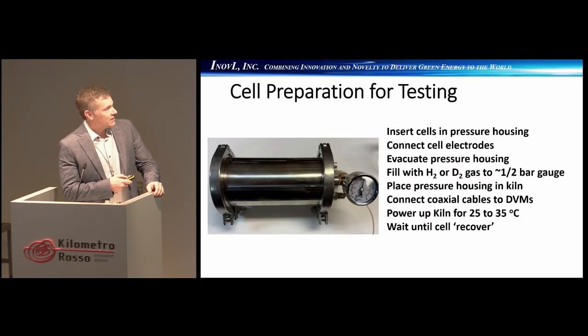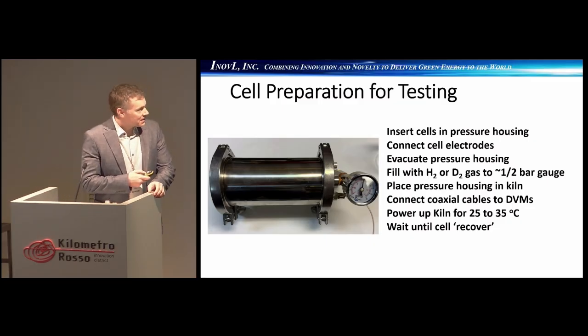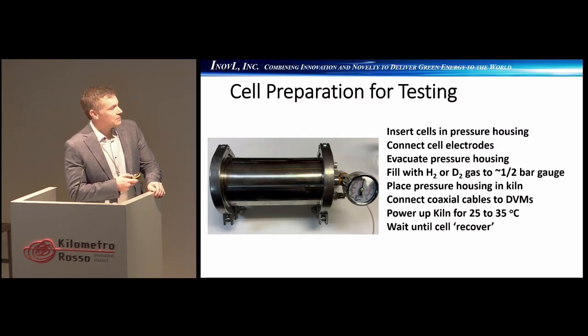And here's just kind of an example of one of our pressure vessels that we use for testing. And just kind of a little bit of housekeeping here of our testing procedure at the time when we were running some of these tests that we're reporting on. Our pressure vessel here, we can take up to a couple bar of pressure. We can accommodate 2 cells at a time for testing. And essentially we'll just take your cell, connect it to the internal leads. You can, if you're doing 2, we have a separator that we put in to keep them from electrical contact and also from electrical contact from the sides.